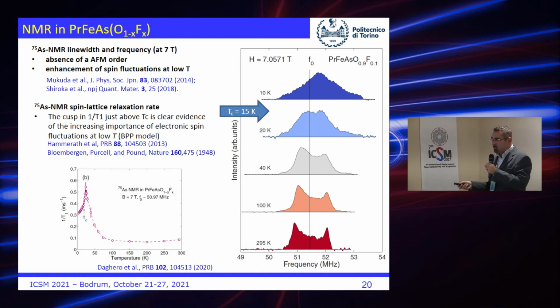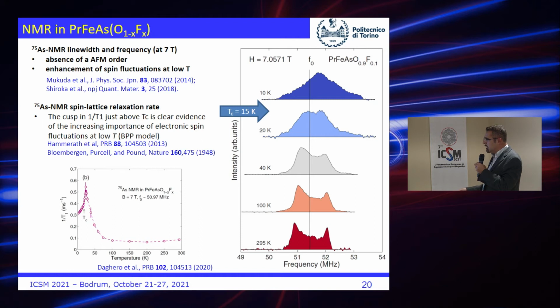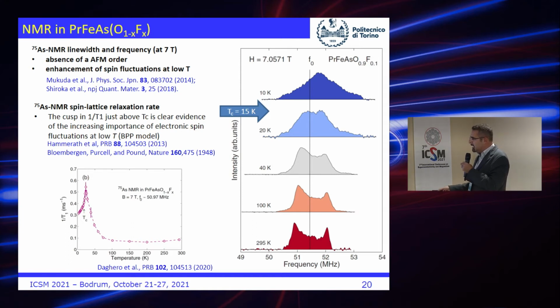That does not order, because there are no abrupt changes, so there is no long-range order. And if you look at the spin lattice relaxation rate, you see that this is regular. This is 100 Kelvin, I think. It's a function of temperature. There is an increase in the 1/T1 when you go down in temperature.